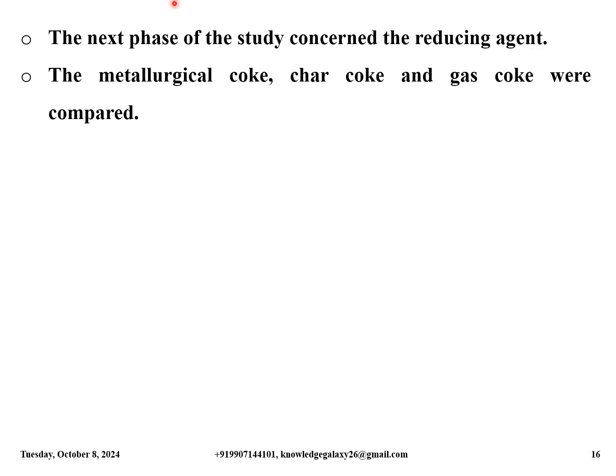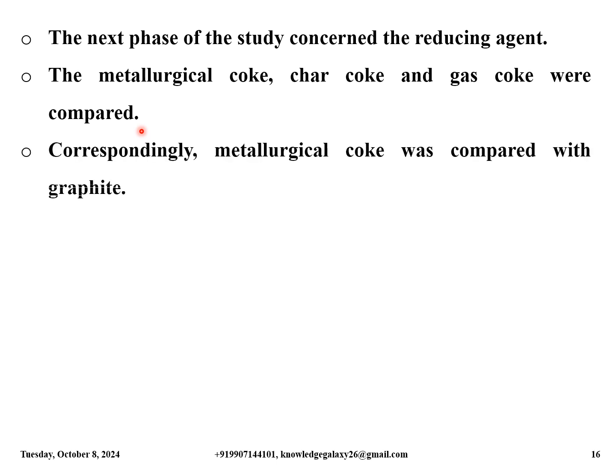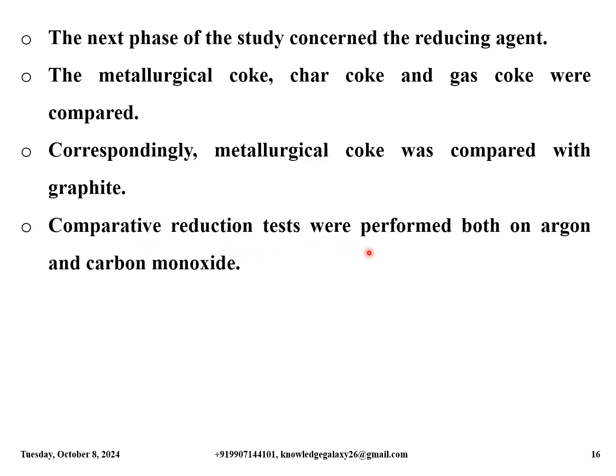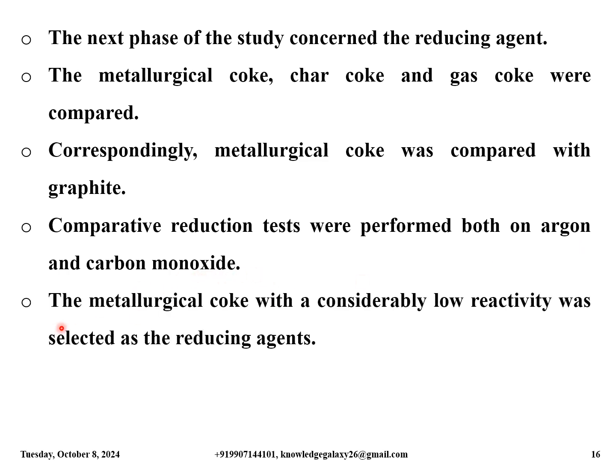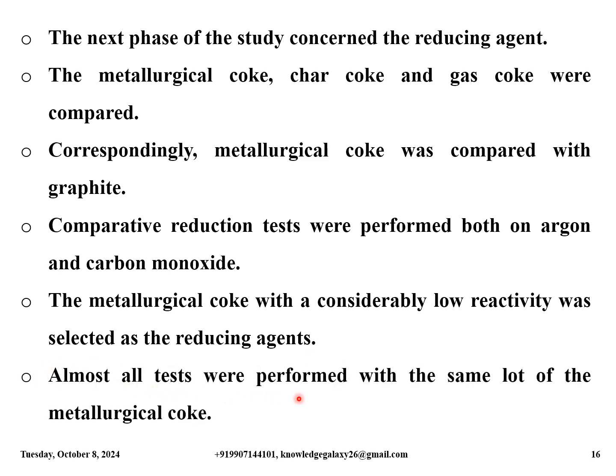The next phase of the study concerned the reducing agent. The metallurgical coke, char coke and gas coke were compared. Correspondingly, metallurgical coke was compared with graphite. Comparative reduction tests were performed both in argon and carbon monoxide. The metallurgical coke with a considerably low reactivity was selected as the reducing agent. Almost all tests were performed with the same lot of the metallurgical coke.